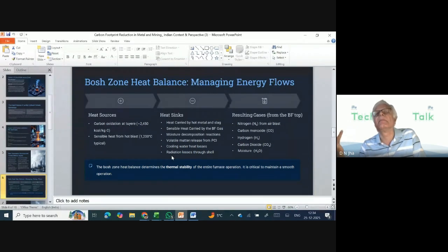We will try and minimize it, but nonetheless there is a heat loss, and we should provide for that. Then the fourth is that, in spite of everything that we do, the shell temperature itself will vary in different operating conditions, from a temperature of, let's say, 70, 80 degrees to a couple of hundred degrees. It does vary. And because of that, there is a radiation loss. So some amount of radiation loss also takes place here.